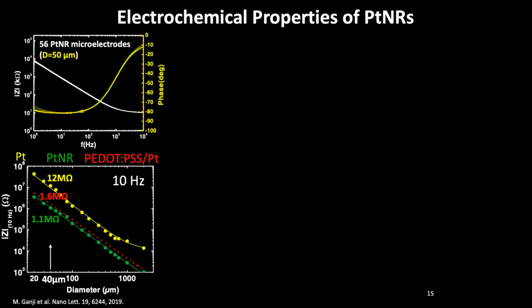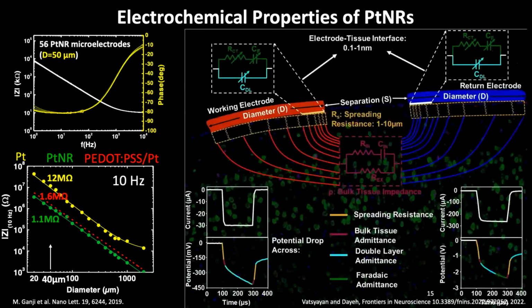On the lower left, we're looking at a comparison of the impedances for planar platinum in green, platinum nanorods in red, and PEDOT:PSS. And we see that platinum nanorods have about one order of magnitude or more lower impedance than planar platinum. So it's there with the class of the highly electrochemically effective materials like PEDOT:PSS. So this is for recording. Again, you want the low impedance for low noise.